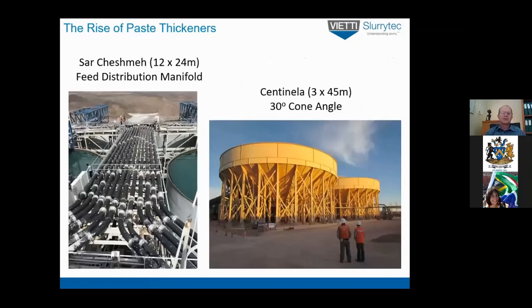The picture on the left is Sar Cheshmeh's feed distribution manifold. That's for twelve 24-meter diameter thickeners. So you can see it's a piping nightmare there to get even feed to all of those thickeners. And even with the big diameter thickeners, with that 30-degree cone angle, when the diameter of a thickener gets large, you basically end up with what looks like a massive pancake with a huge cone on the end, and you need enormous structural capability to hold that steel work up. So it becomes impractical to have the deep cone paste thickener for very large applications.